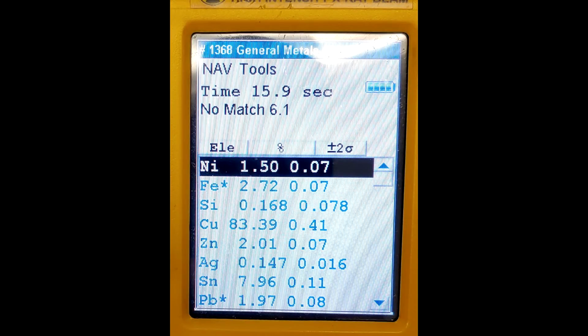Here is the XRF results from our first control button. This was the computer parts with no oxide and no iron. And you can see it's mostly copper. There's a little bit of nickel, iron, and zinc in there. Silver actually shows up. Then you see tin makes up about 8% of the button, and then lead brings up the bottom at 2%. This is a good example of just run-of-the-mill PC boards and the metal concentrations that they have.